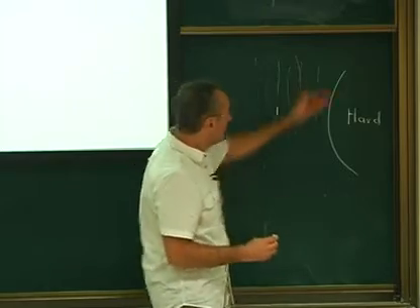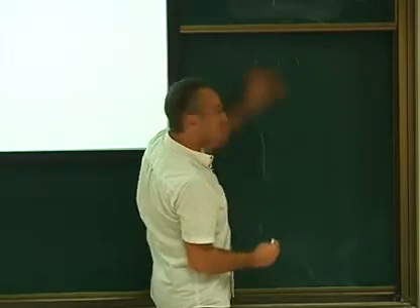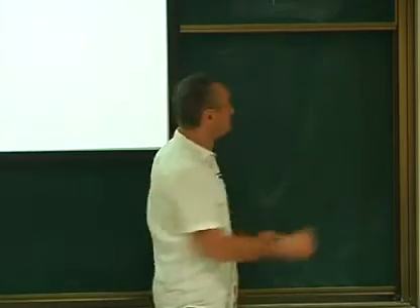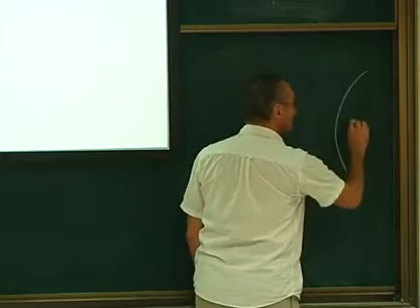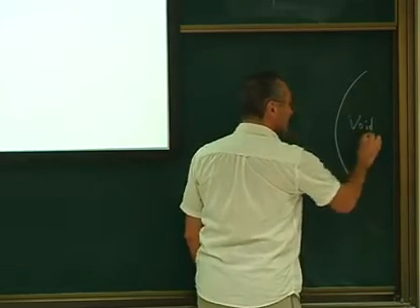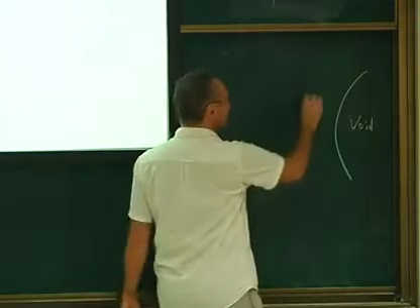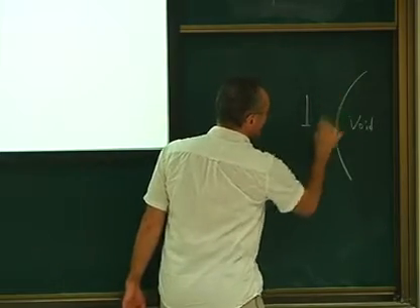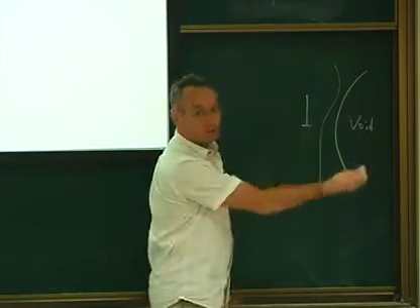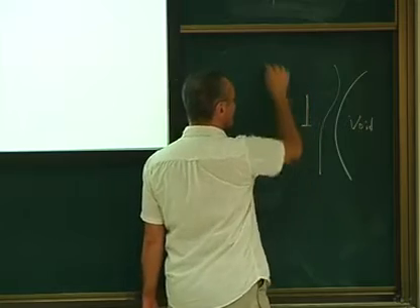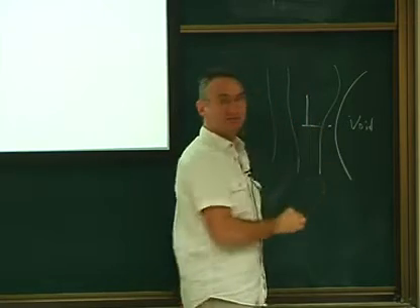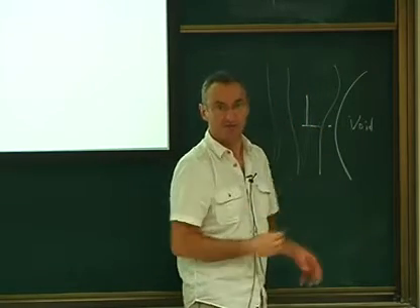So this is important. And now if you do the same, but you have a free surface, something soft, a void, typically. It attracts, yes, it's a void. So the void is soft, it can deform very easily. When your dislocation comes, this bending of the plane will be even more bent like that than expected. So the dislocation will move easily to the void, so it will be attracted by the void.